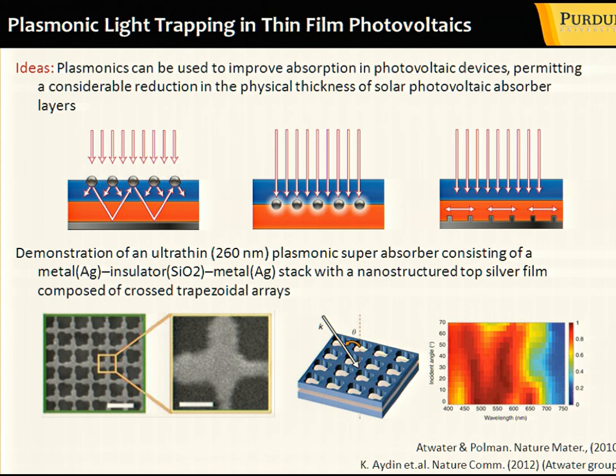And the idea typically here is related to one of these three approaches. In one case, you place these metallic particles to simply induce this broad angle scattering so that you effectively increase photon propagation length in the solar cell, or you could simply rely on the enhanced local fields produced by these plasmonic nanoparticles, and by doing so, you would increase the efficiency of electron hole generation. Finally, you could also use these periodical metallic structures, which are capable of excitation and supporting surface plasmon polariton, which effectively also increase the optical propagation length in solar cells. Those are three different approaches which people use to try to bring plasmonics into the field of photovoltaics.